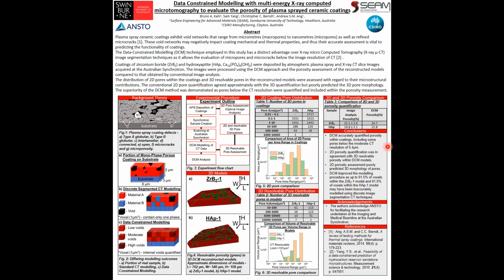Thus, to conclude, data-constrained modelling accurately quantified the porosity within coatings, including some pores below the CT resolution, as shown in Figure 6, even with a moderate CT resolution of 5.4 micron. The 2D quantification of porosity was in moderate agreement with that obtained from the 3D models. However, the 2D pore assessment poorly predicted the 3D morphology of voids. As such, any properties strongly dependent on the 3D microstructure of coatings, such as thermal conductivity, cannot be accurately inferred